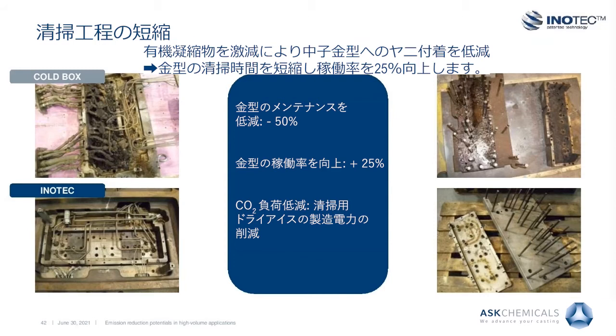Besides the ecological benefit of missing emissions in the casting process with INOTEC, savings in cleaning maintenance for the permanent die mold are a result as well. When casting with organic sand cores, the buildup of condensate occurs on the permanent die mold, which must be removed by employees in regular intervals to ensure correct functionality, especially of movable parts. The physical strain for employees involved in this work is high. In addition, there's a very high level of noise pollution.